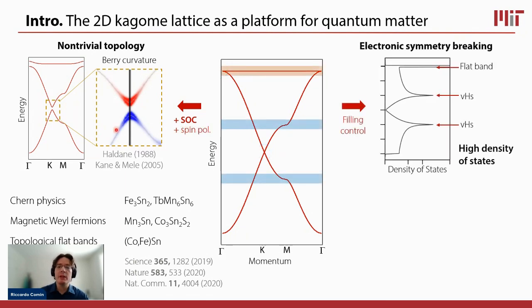If we play with filling control, so if we imagine that hypothetically we can move the chemical potential anywhere we like in this band structure, and if we place the chemical potential at one of the places where the density of states is diverging, so the flat band or the Van Hove singularities, then what will happen is that the system will not like to have a high density of states at the Fermi energy.